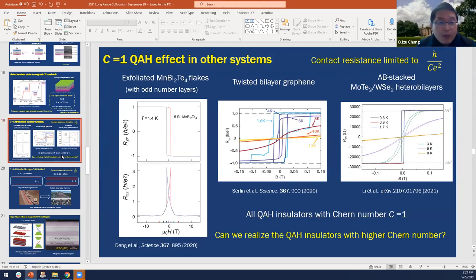Thanks, David. And let me comment on this also. Usually in the magnetically doped TI, we perform the measurement at very low temperature. But I want to say something related to the twisted system. We can see that in the twisted system, when the longitudinal resistance is finite, the Hall resistance is already greater than h over e squared. That I never see in the magnetically doped TI system.